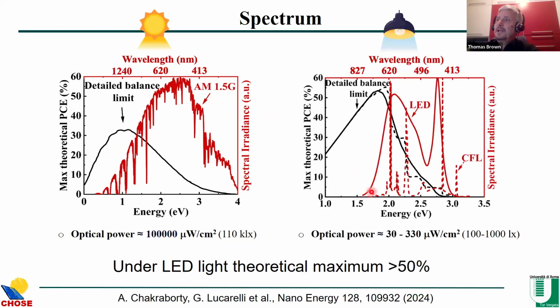indoors, the spectrum is much narrower and concentrated in the visible, so between 700 and 400 nanometers, so between 1.7 and 3 electron volts in terms of energy. So being much narrower and towards the visible with no infrared, then you can do the detailed balance limit again, and you see that the best band gap is around 1.8, 1.9 electron volt, not between 1 and 1.5. And the efficiency increases to over 50%. So more than half of the optical power can be transformed into electrical power. That's why, you know, indoor photovoltaics can be so exciting.